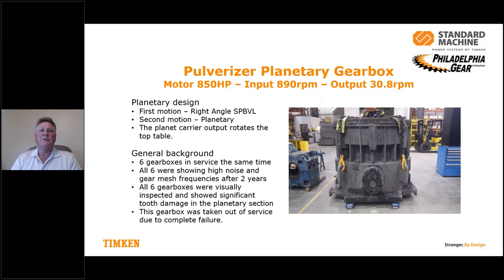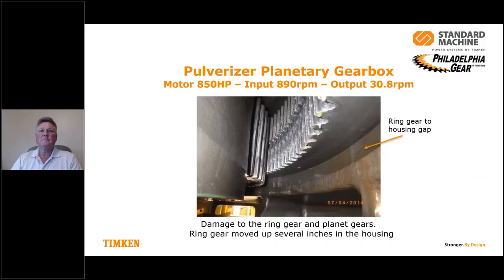So the general background here, when we got this gearbox, we learned that there were six gearboxes all put into service at the same time, and all six were showing really high noise and gear mesh frequencies after 2 years of service. The gearboxes were inspected, and they saw an awful lot of tooth damage in the planetary section. Because of the customer situation, they had to continue running these gearboxes. And this gearbox was eventually taken out of service because of a complete failure. So let's look at what we found.